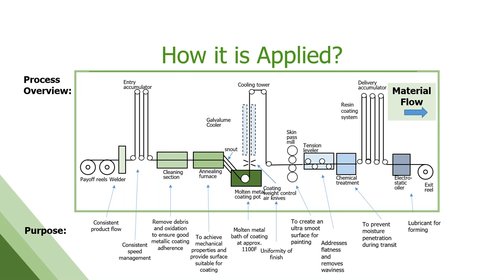Starting left to right, we load, we got two coils on the payoff reels and it goes through the entry accumulator. These accumulator towers are what allow us to run continuously by changing the length of the line. Those rolls move up and down to either lengthen the line or shorten the line. Goes through a cleaning section. We got to get that steel really clean, get all the oxides and debris off of it before we coat it. Goes through an annealing furnace.